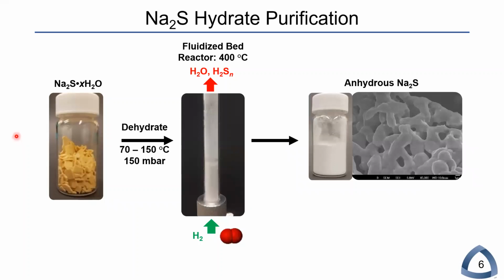The sodium sulfide hydrate purification process is outlined on this slide, with an image of the as-received sodium sulfide hydrate shown here on the left. After grinding this material to reduce the particle size, it can be thermally dehydrated at 70 to 150 degrees Celsius under reduced pressure to produce an anhydrous technical grade sodium sulfide.